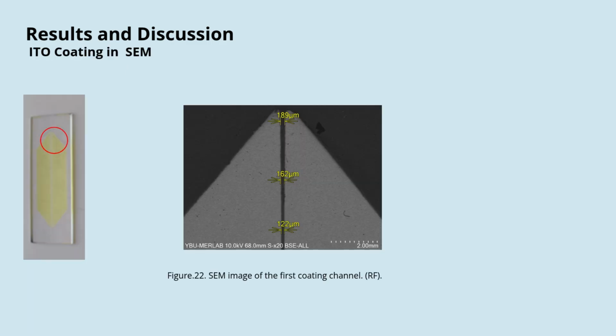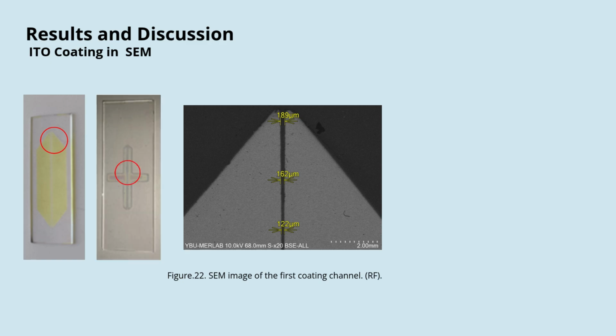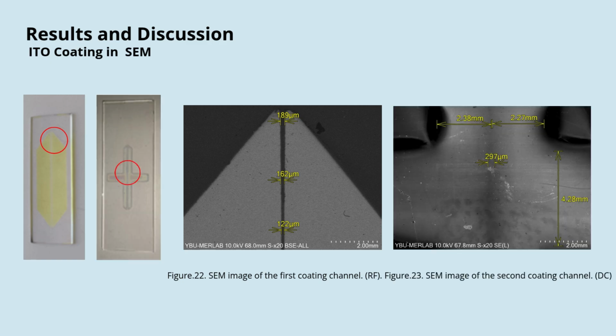SEM image of the first coating shows that the channel gap is getting narrower. This indicated that there was a leakage under the mask in the sputtering process. For the second coating, the channel gap is not as prominent as the first coating. This could be attributed to its thinner ITO layer. There is not enough material to show a deep channel.